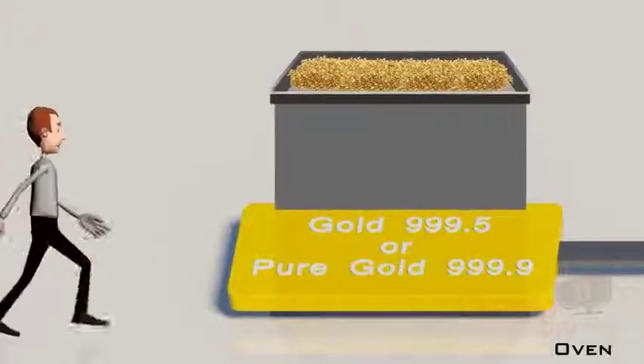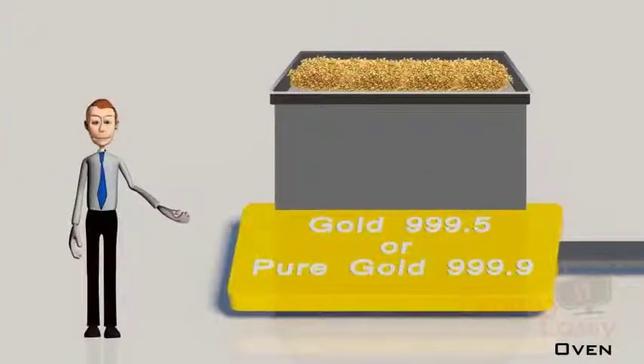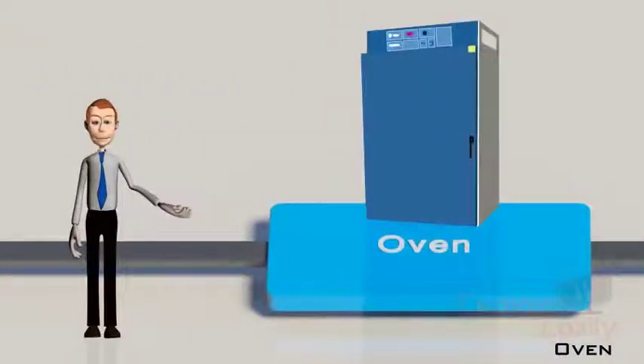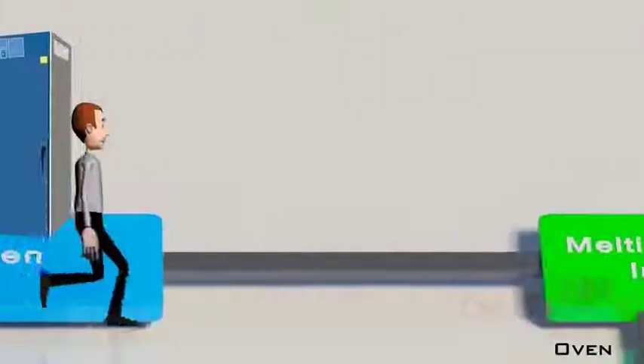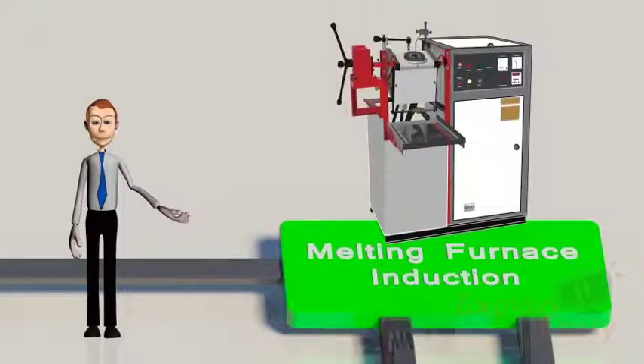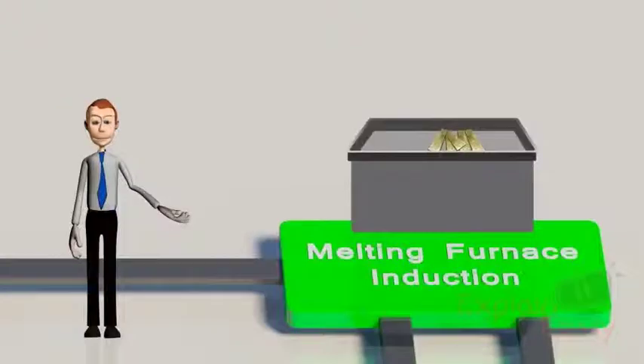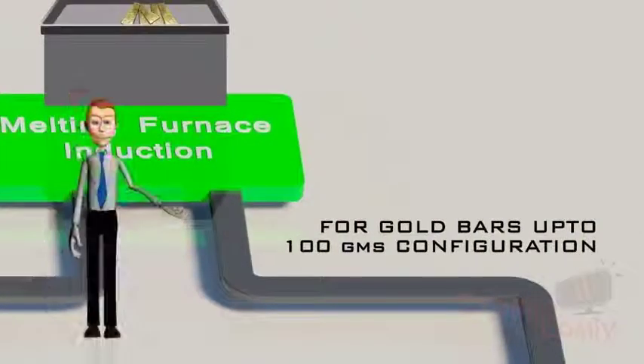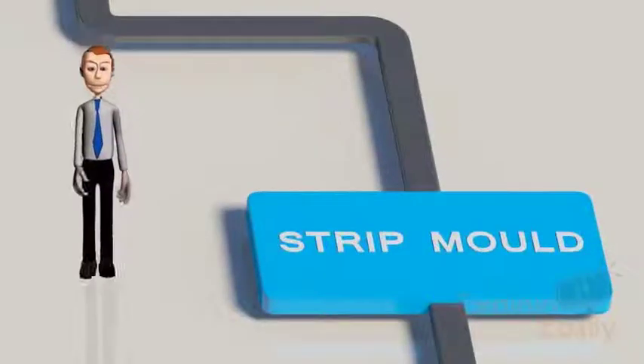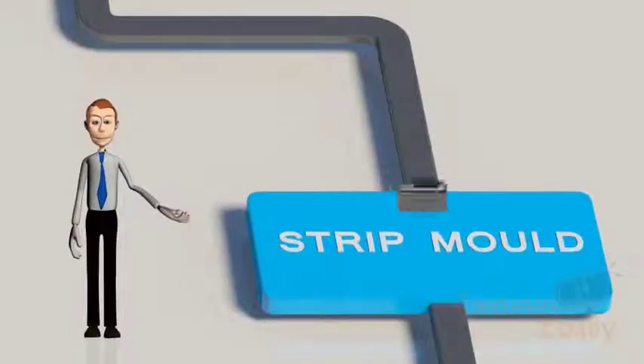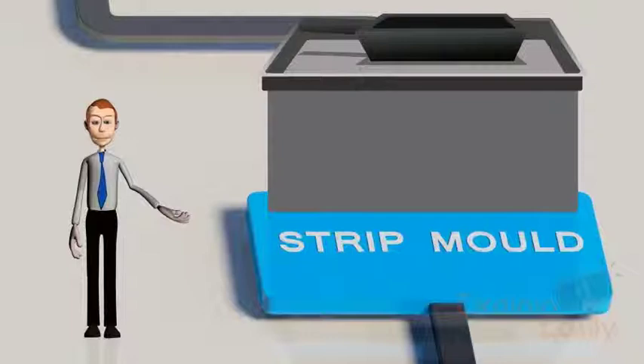The pure gold sand of 999.5 generated from the aqua regia process is first dried in an oven, or it can be pure gold of 999.9 from electrolytic process. This gold is then melted in an induction furnace, whereafter it follows the process depending on the configuration of gold bar desired. For gold bars up to 100 GMS configuration, the molten gold is collected in a pre-designed mold for the desired configuration in strips.